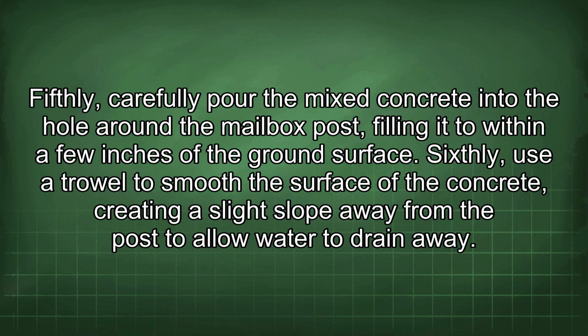Fifthly, carefully pour the mixed concrete into the hole around the mailbox post, filling it to within a few inches of the ground surface. Sixthly, use a trowel to smooth the surface of the concrete, creating a slight slope away from the post to allow water to drain away.